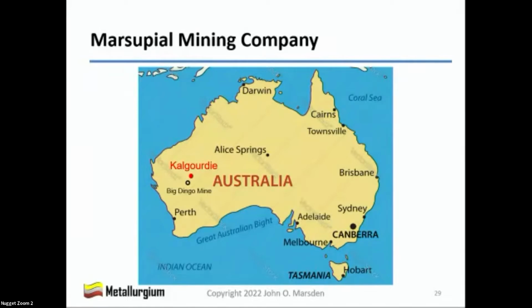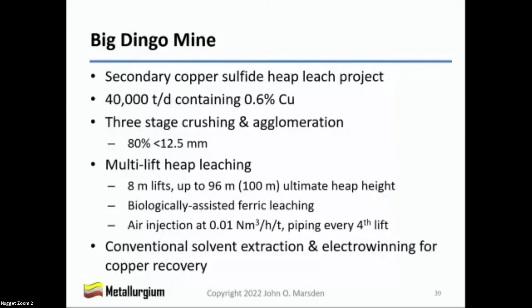It was a medium-sized copper operation, processing 40,000 tons per day of ore containing 0.6% copper. Next slide. The ore was crushed to 80% passing 12.5 millimeters. It was agglomerated with sulfuric acid and leached on a lined heap leach pad. Copper is recovered from the leach solution using conventional solvent extraction and electrowinning. The expected metallurgical recovery was 76%. The annual copper production was budgeted at about 66,500 tons.